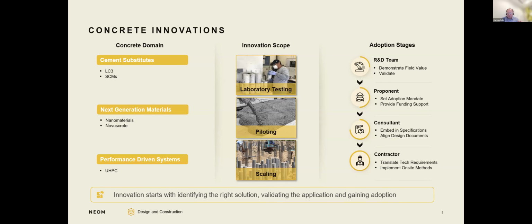So the department that I lead is responsible for the technical work and developing the template mixes. So what we did was we approached a series of laboratories, both university and private laboratories in Saudi, to develop mix designs using various supplementary cementitious materials that would meet all of those objectives. And they were the known technologies of byproducts of other industries such as GGBFS and fly ash, a lot of work with natural pozzolans that are locally available in the Kingdom, and silica fume for dense packing and improved durability.